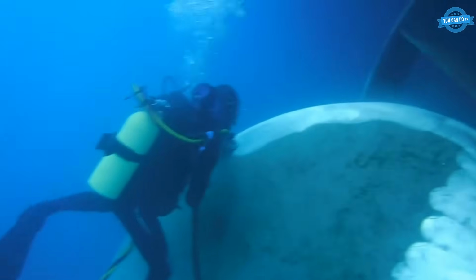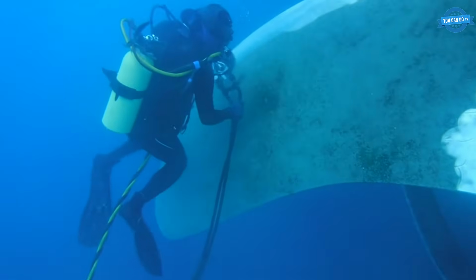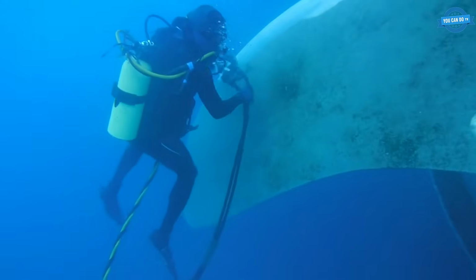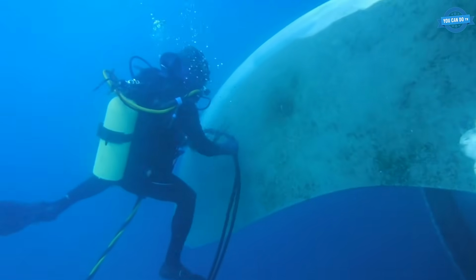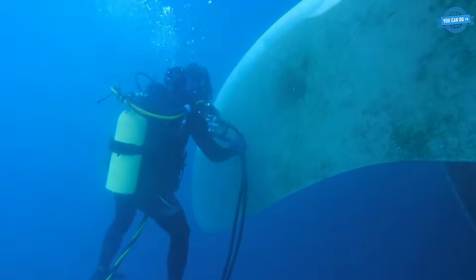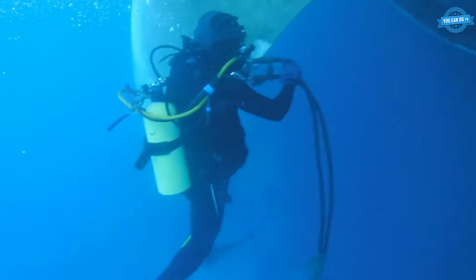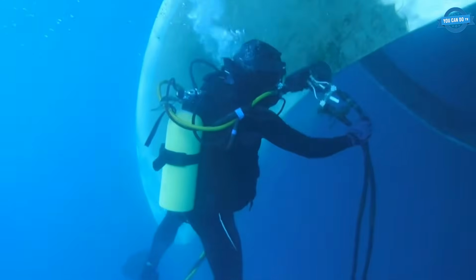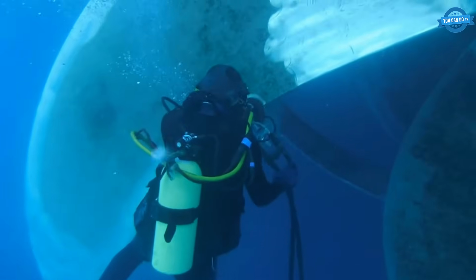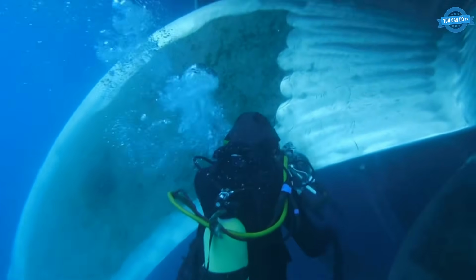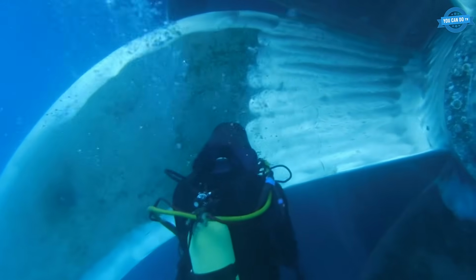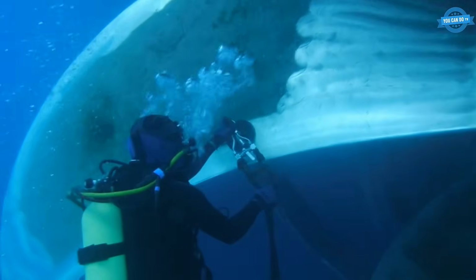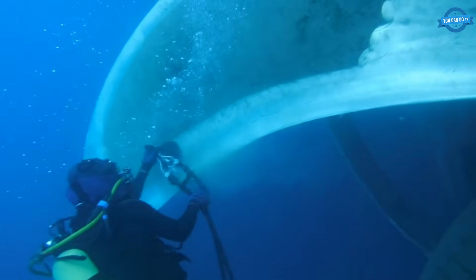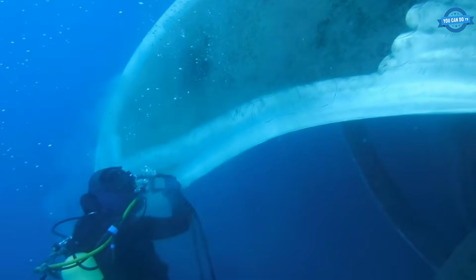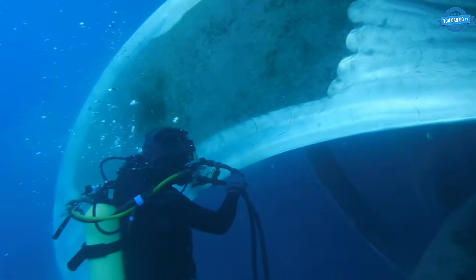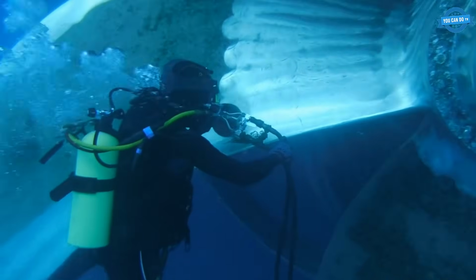While fatigue works from inside the metal, the sea attacks the surface from outside, slowly and chemically without stopping. A diver descends to a large propeller still mounted under the hull, carrying a hydraulic polishing tool fed by a line from the surface. The blades have gone dull, coated in marine growth and the staining that seawater leaves on bronze over months in the water.